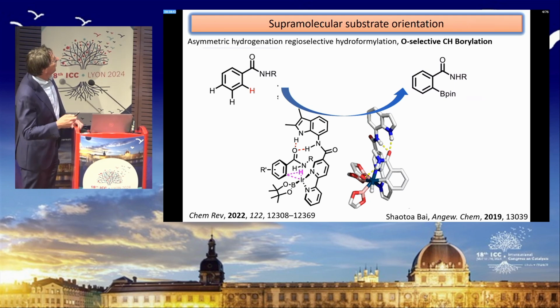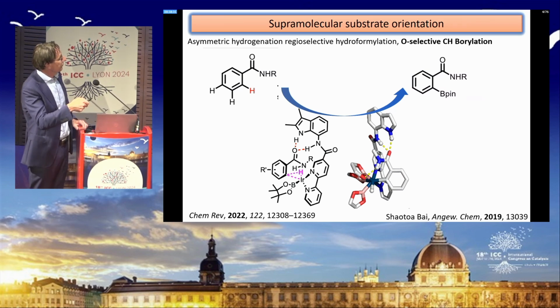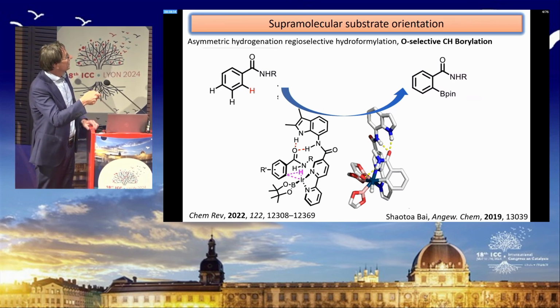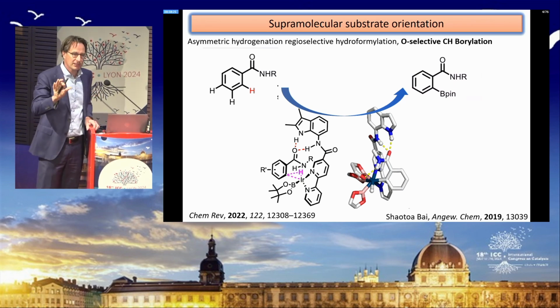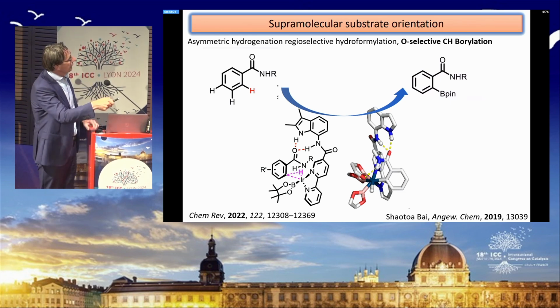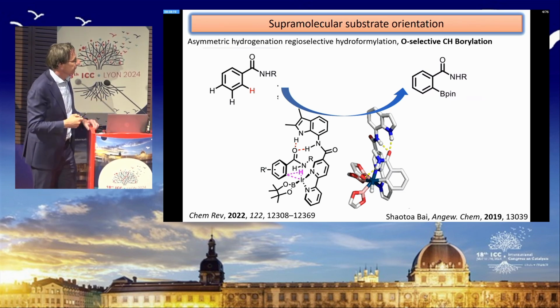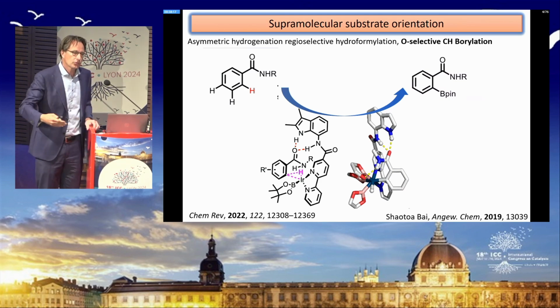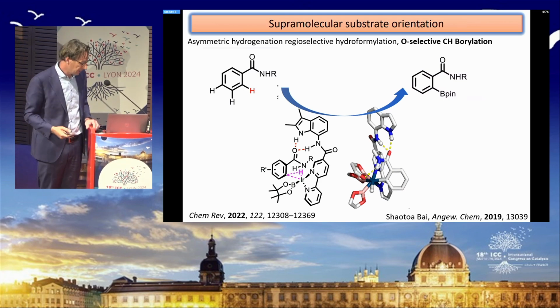So here you have an example of supramolecular substrate orientation. In this particular case, we looked at selective ortho-borylation, which is typically going for the para or the meta substitution. But if we do substrate orientation by hydrogen bonding, we fix the substrate at a certain position at the metal center, and then we get mainly the ortho-borylated product, and we extended this concept to hydroformylation, hydrogenation, etc.